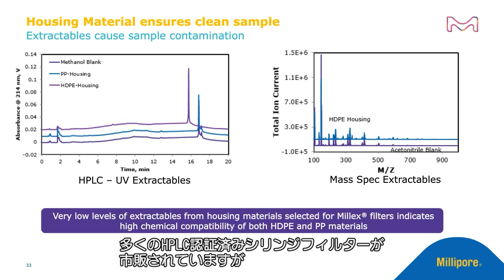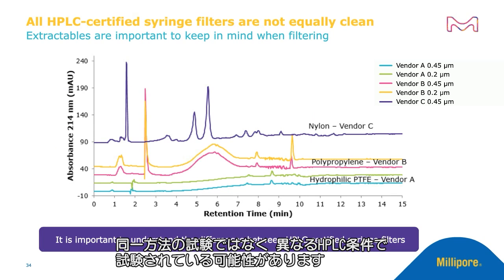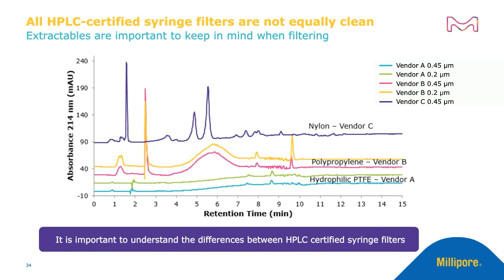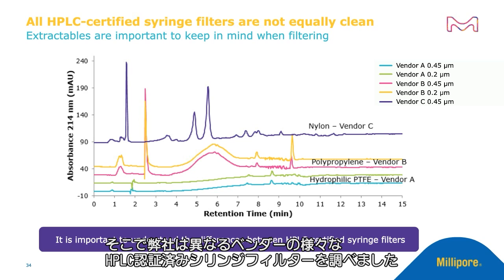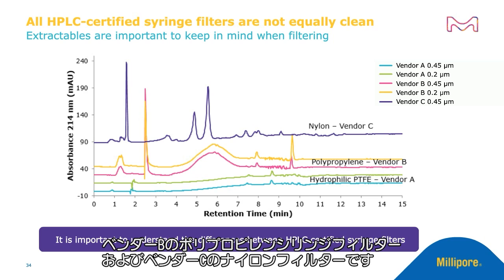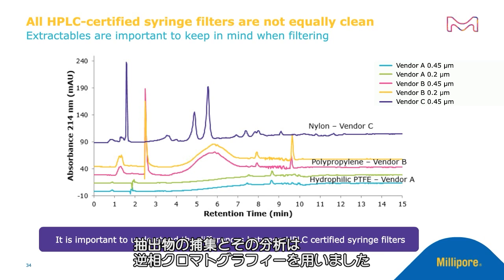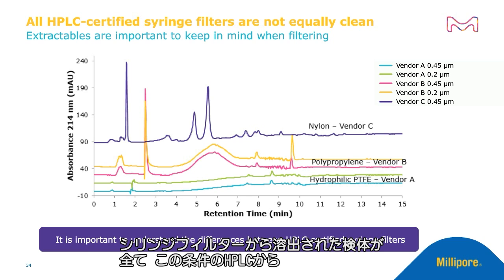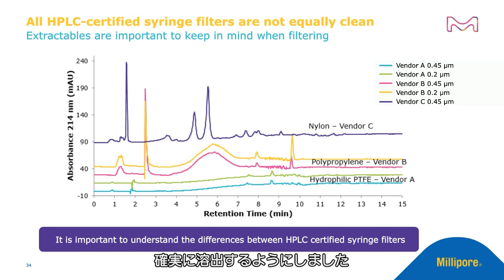In the market, there are a number of HPLC certified syringe filters. But these syringe filters are not tested exactly the same way, and they may be tested under different HPLC analysis conditions. So we looked at various HPLC certified syringe filters from different vendors. The hydrophilic PTFE syringe filters are from Millipore Sigma, the polypropylene syringe filters from vendor B, and the nylon from a vendor C. These syringe filter extractable analyses were carried out by filtration of 70% acetonitrile and 30% water through these syringe filters, collecting this extract and analyzing it using reverse phase chromatography. We used a 0 to 100% acetonitrile gradient to make sure that all the analytes that were extracted out from this syringe filter will elute under these conditions.